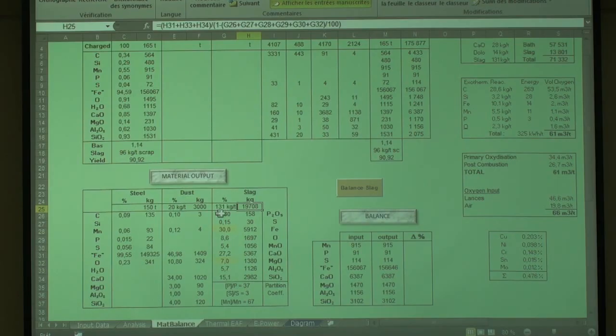So I am able to calculate the P2O5 content of the slag, thanks to the equilibrium between the slag and the steel, by this formula we have seen yesterday. I am able to calculate the sulfur content of the slag as well. I am able to calculate the MnO content of the slag by the equilibrium as well. MgO is an input. This is the target MgO content I want in the slag.